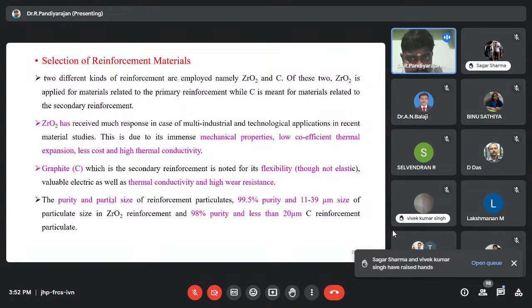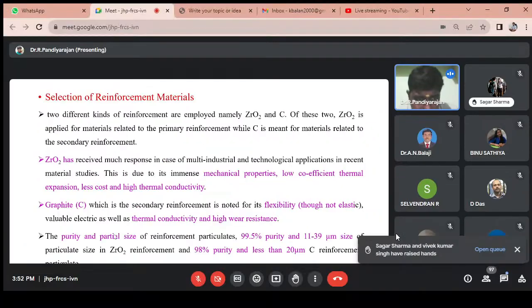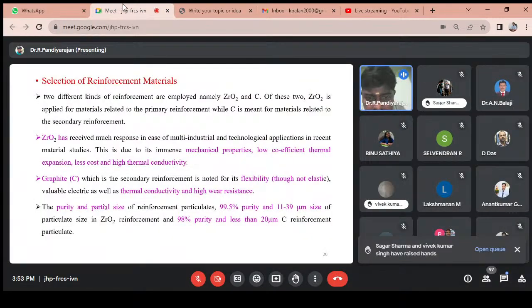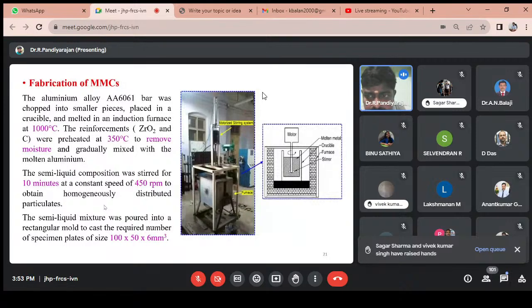We also utilize graphite. Graphite is a secondary reinforcement particulate. It is used to improve the tribological behavior of the composite material. Once the researcher buys both materials, the matrix material and the reinforcement particulate, we definitely check the purity and particle size of the matrix and the reinforcement particulate. There are many types of purity available in the market. From a research point of view, we need more than 90% purity and less than micron size also. Definitely measure that. After that we fabricate the metal matrix composite material by using the stir casting method.